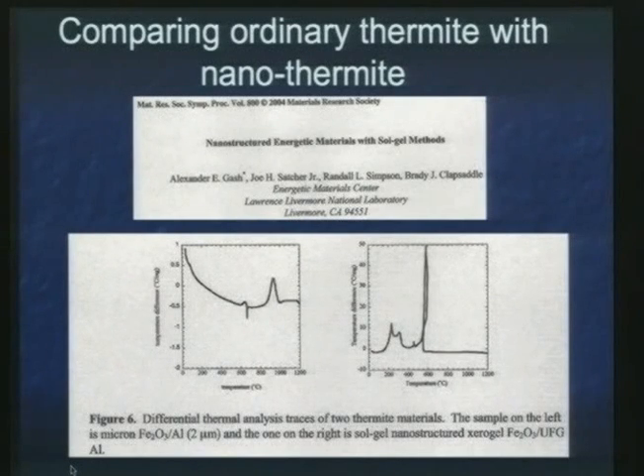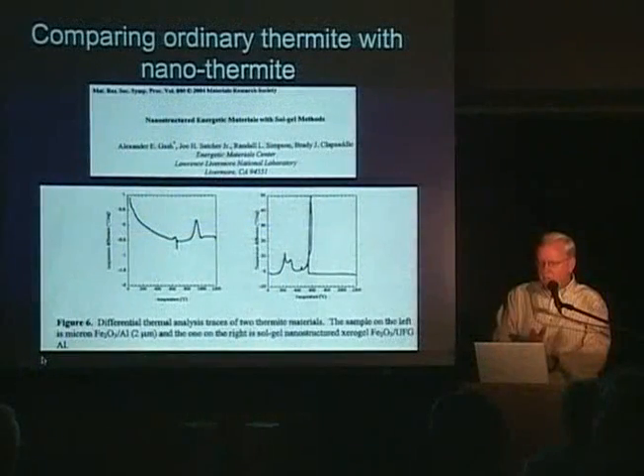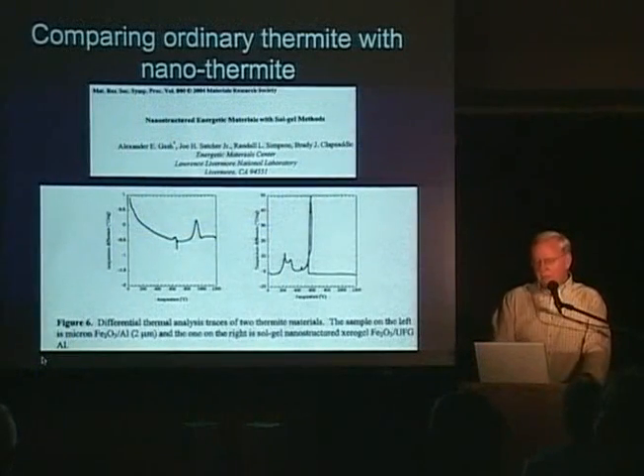If I can help you read the scale, the ordinary thermite goes off at about 900 centigrade, and their nanothermite goes off at just below 600. It's about 550 in this case, centigrade. Again, the finer the material, the lower the temperature. So that distinguishes, again, nanothermite from ordinary. Notice how much broader the ordinary thermite peak is compared with nanothermite.